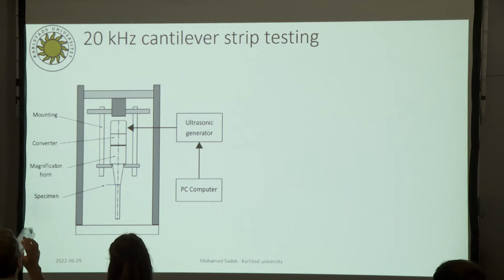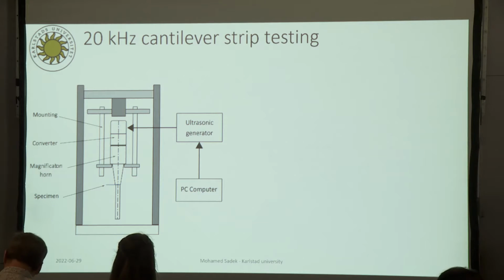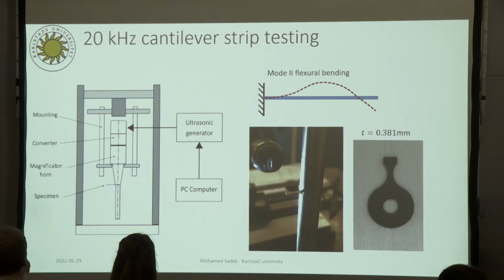The idea was first seen on a brochure by Shimadzu, the company, where they showed a similar setup. They have the horn, a 20 kHz horn, where they clamped a strip steel specimen just below the horn right here. We took this idea further and designed our own specimen. We included a waist into the specimen, inspired by previous testing on strip steels at lower frequencies.